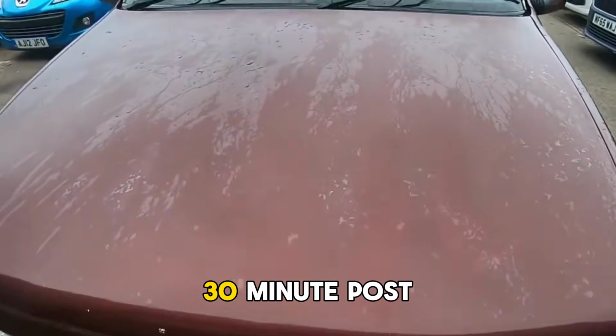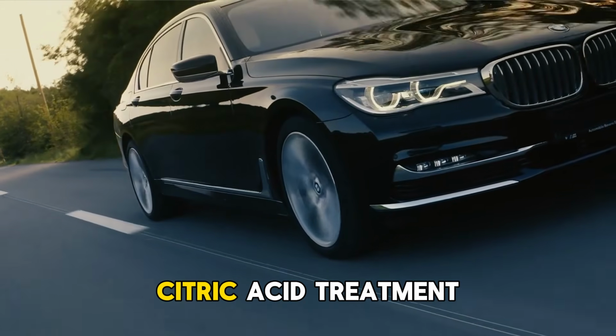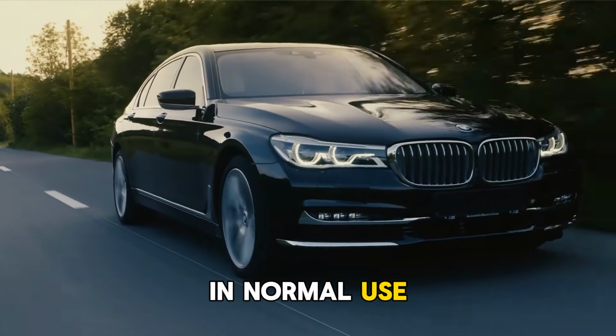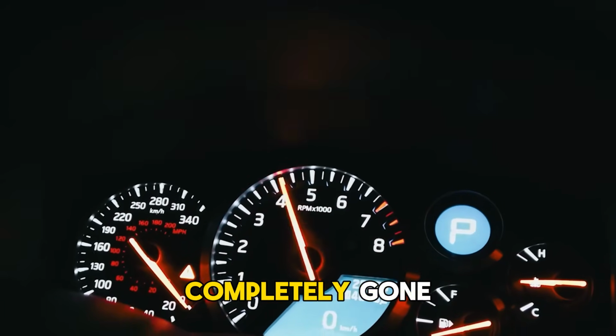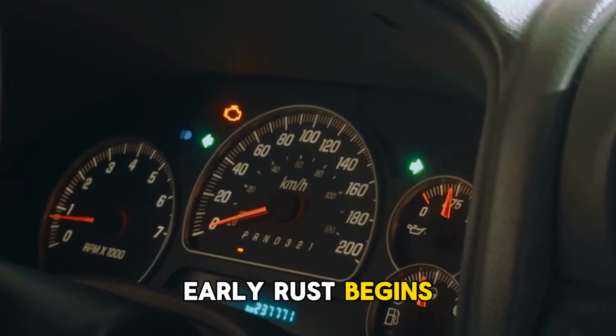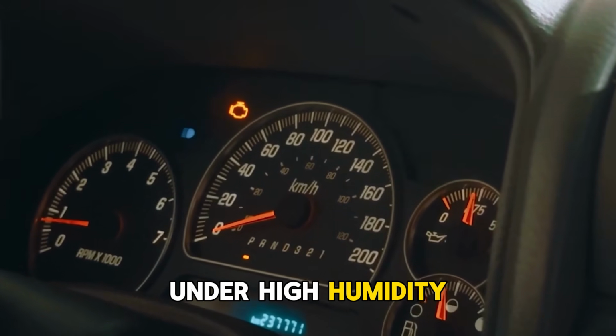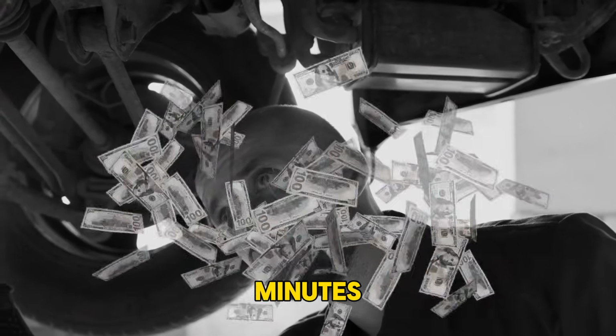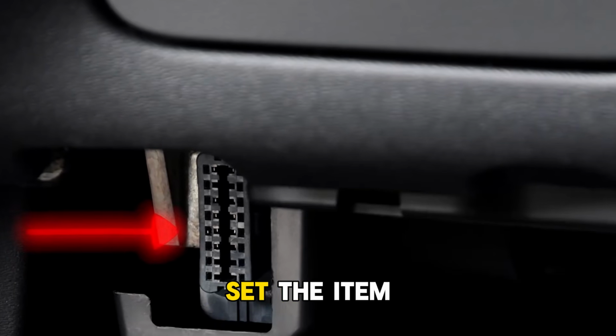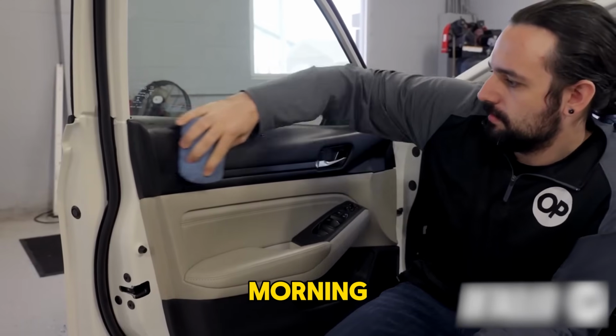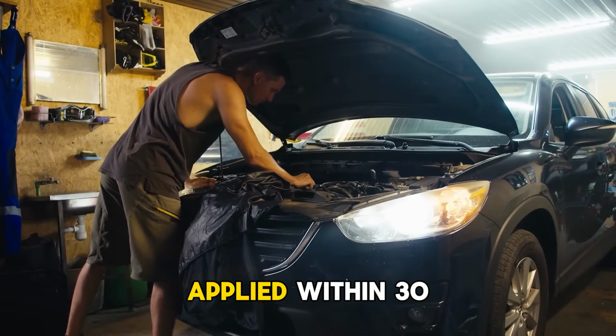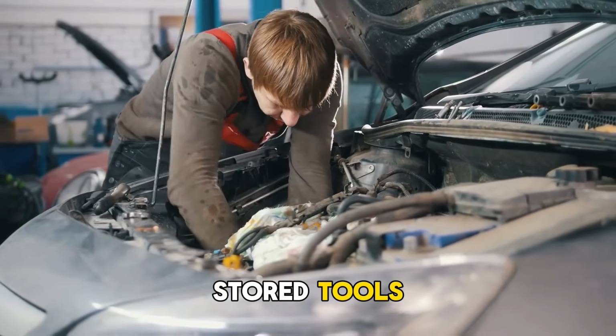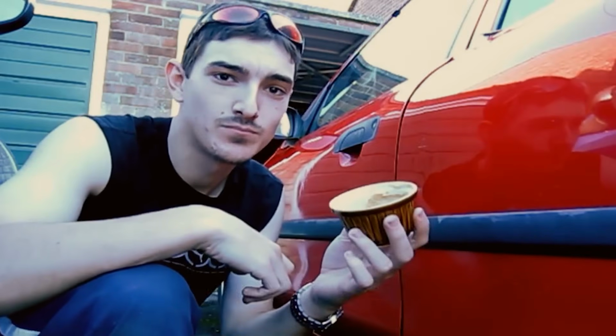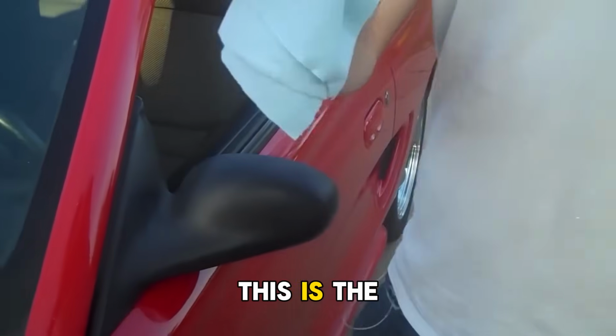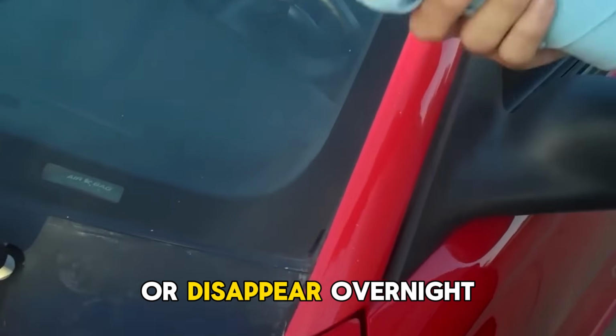Number 10. The 30-minute post-treatment rule. Bare metal after citric acid treatment is the most reactive surface in normal use. The natural protective oxide layer is completely gone. In humid air, early rust begins forming within 2 to 4 hours. Under high humidity, visible orange spots appear within 30 minutes. Most people complete a successful treatment, set the item aside, and find rust returning by morning. The treatment did not fail. The protocol was left incomplete. Protection must be applied within 30 minutes of drying: penetrating oil for stored tools, self-etching primer for surfaces going to paint, seasoning oil in a hot oven for cast iron. This is the step that determines whether results last years or disappear overnight.